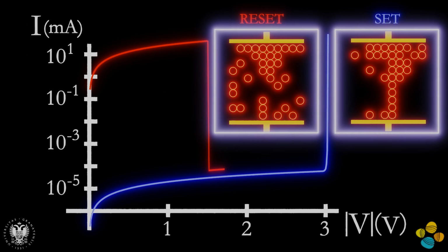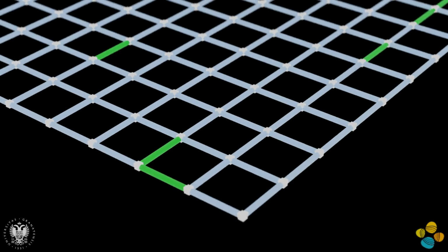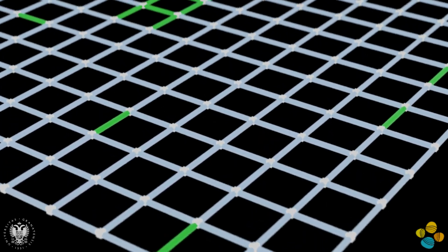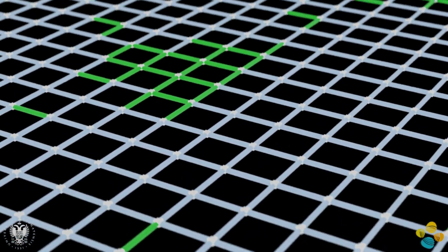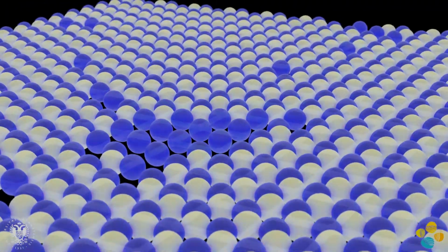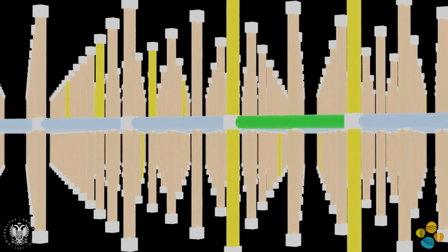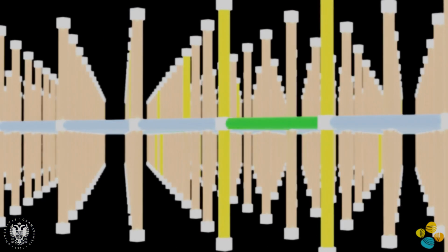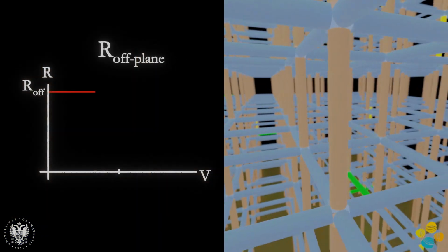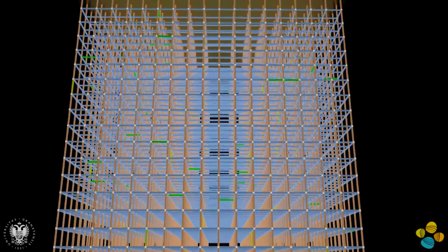The resistances of the simulator network can be switched between 4 different values, as if they were complex circuit breakers. Different resistance values are used for the circuit breakers in the planes, corresponding to the boron nitride layers, and the vertical circuit breakers to reproduce the features of two-dimensional materials. A device with a pristine dielectric is assumed to start the simulation.